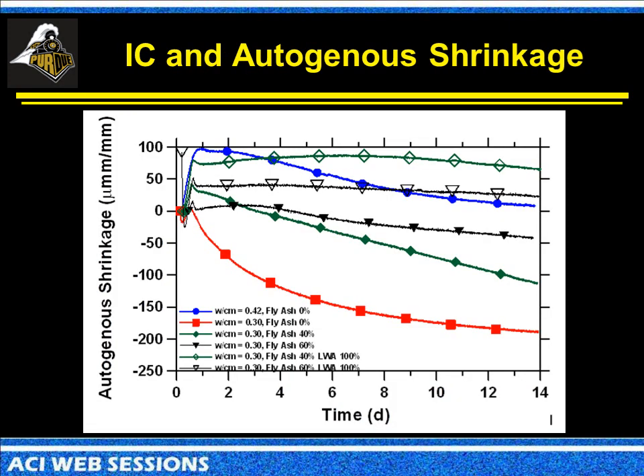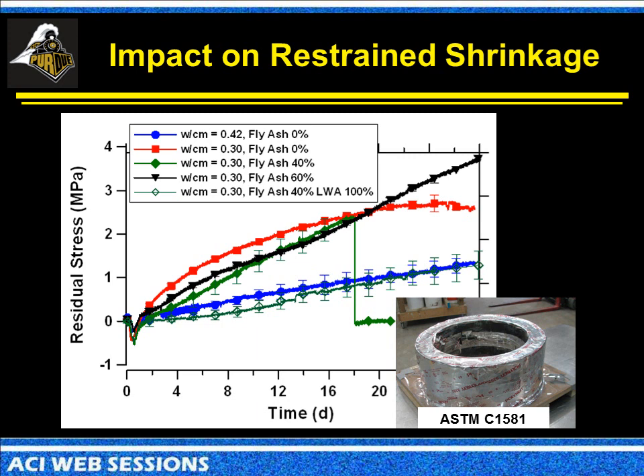When we look at autogenous shrinkage, we can see here that, again, this was our 0.3 before. This was our fly ash system. When we internally cure the system, we have a slight expansion, and then we see the autogenous shrinkage staying relatively constant and relatively low in the overall case. Now, I think this is the most important of the takeaway slides when we start to look at the real benefits of internal curing as it relates to autogenous shrinkage.